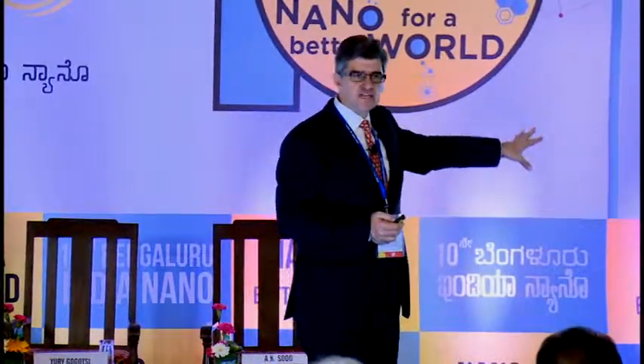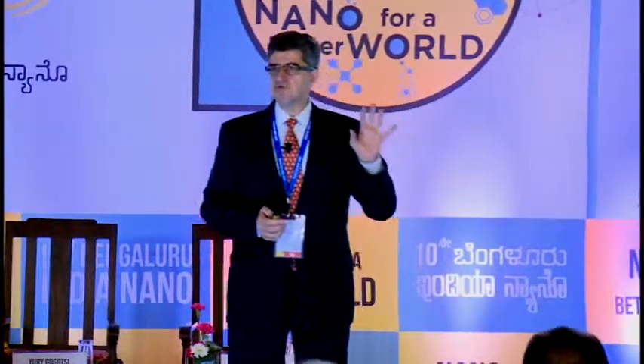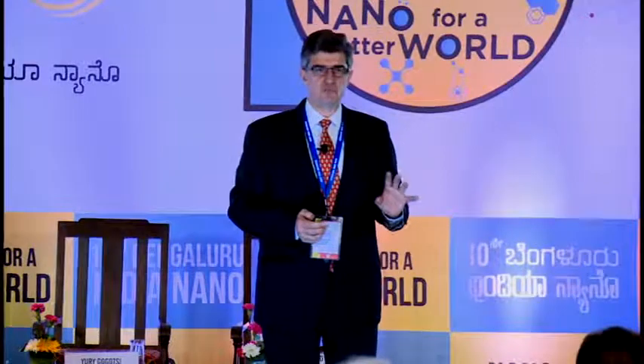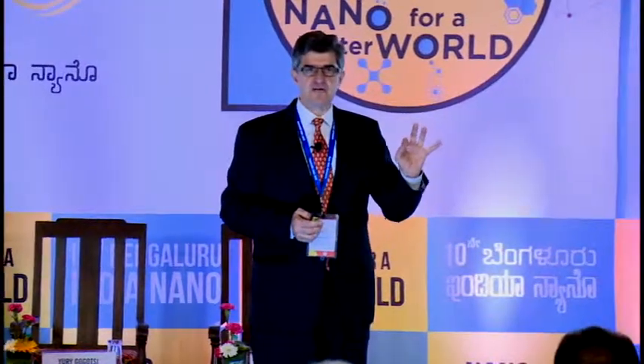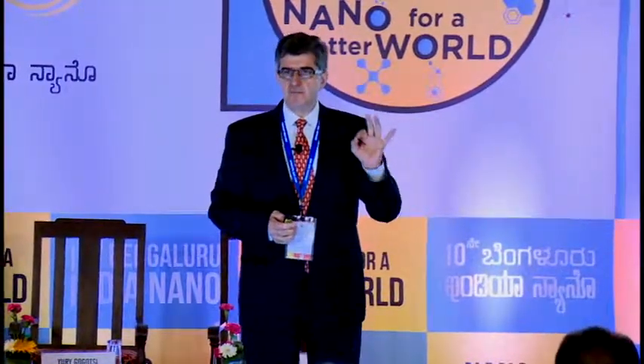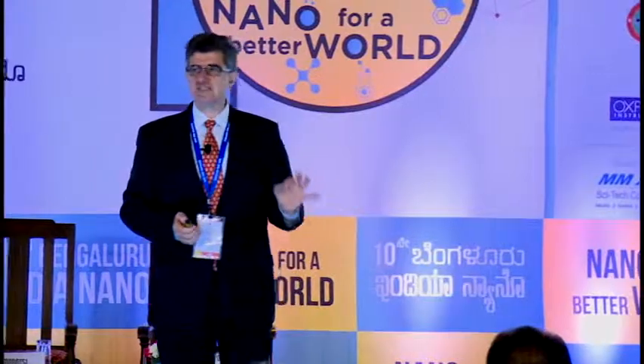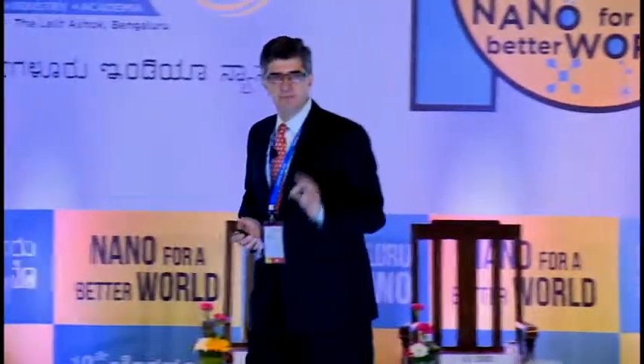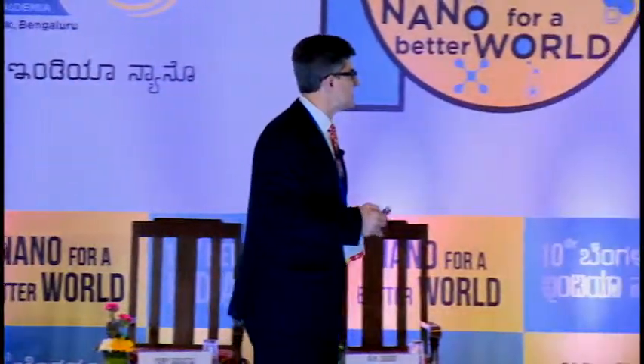This is a sulfuric acid electrolyte, like in a lead acid battery here. It's not necessarily optimum, but what this work showed was very, very fundamental and very, very important. It shows that we're not limited by redox reaction for high rate storage. So fundamentally, it is possible to have redox energy storage, like in a battery, but with extremely high rates. We just need the right materials, correctly designed materials.